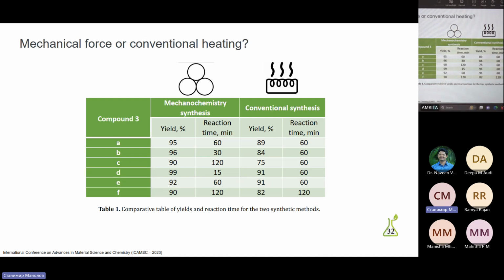A noticeable reaction occurred in all instances, and the reaction duration varied depending on the specific starting amide 2 which is used. The shortest reaction time was observed with amide 2D, characterized by the presence of two electron-donating methoxy groups within the benzene nuclei. This configuration facilitates complete cyclization in just 15 minutes.